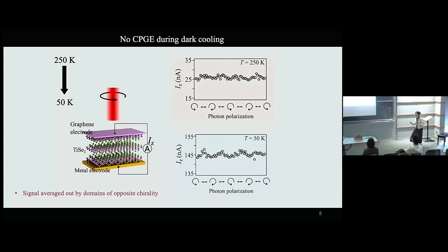So the other possibility is, if you think about a ferromagnet, right? The ferromagnet has spin up, spin down, and how do you get a single domain? You use a magnetic field to train this material, right? During cooling, or at low temperature, you apply a large magnetic field. And the field cool is usually more energy efficient. That's what we try here.